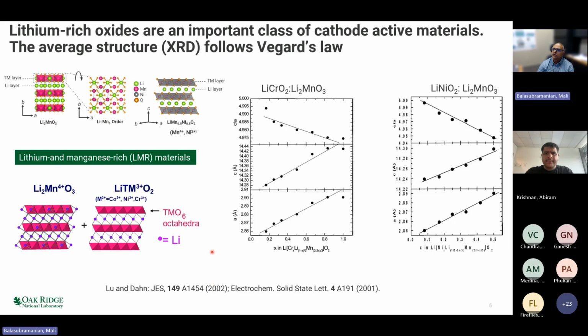In these systems, what happens is two different end members, for example, Li2MnO3, which is a lithium-rich phase, and a regular conventional layered component, which is LiTMO2, like lithium cobalt oxide, for example, are intermixed at an atomic scale. Now, if you take these materials and mix them at an atomic scale, what you find with diffraction is that as the composition is varied, this value x is varied, the lattice parameter changes continuously in such a way that it follows Vegard's law.